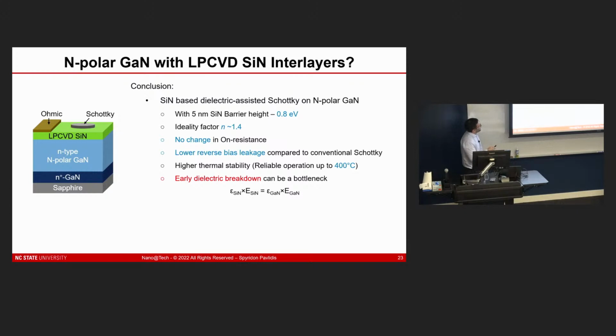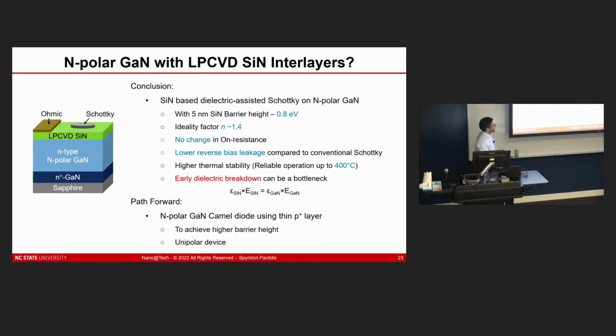So that is all well and good because we can show low ideality factors and engineered interfaces and so on. Because the interlayer is so thin, we have negligible change in the on resistance as well. But the biggest problem in terms of high voltage is that if you use the silicon nitride layer, ultimately you might see breakdown happening or bottlenecked by your dielectric. So we were thinking about a different way that we can do this that would really leverage the wide bandgap properties of gallium nitride, but still allow us to tune that barrier height and get better performance.